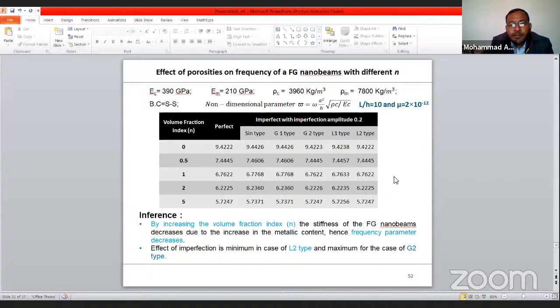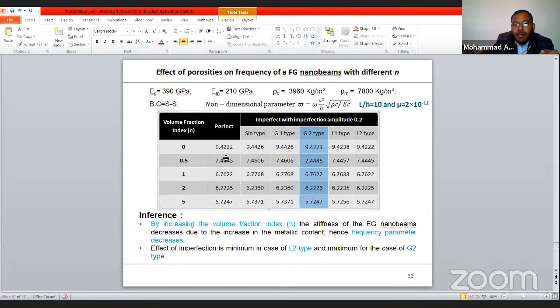Here, the effect of various geometric imperfections are presented. For this particular result, I have considered the geometric imperfection amplitude eta is equal to 0.2, and for the perfect structure, the geometric imperfection amplitude is 0. For various volume fraction index, the results are presented here, and we found that on increasing the imperfection amplitude, the frequency parameter is increasing. But in case of G1, G2 type, the effect is maximum in case of G2, and in case of L2 type, the overall effect is minimum.